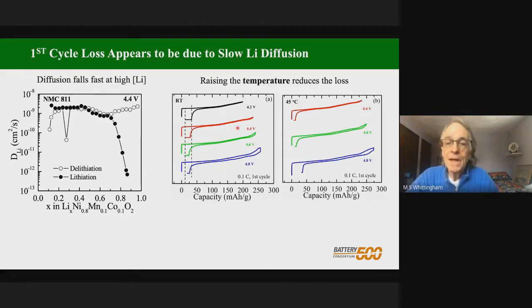So what we decided to do is the same experiment at an elevated temperature. So we raise the temperature to 45 degrees centigrade. And I just show you the three here because the black one is too low a capacity to be of interest. You can now see that we've recovered much more of the lithium at 45 degrees, and holding at 4.8 volts gets us a bit more back, but not that much more.